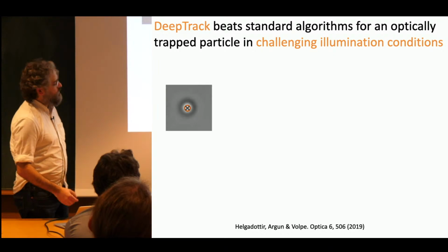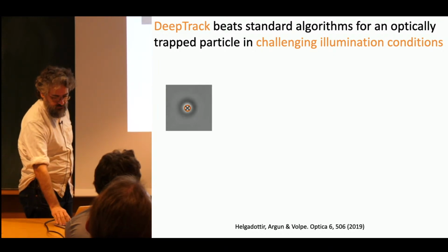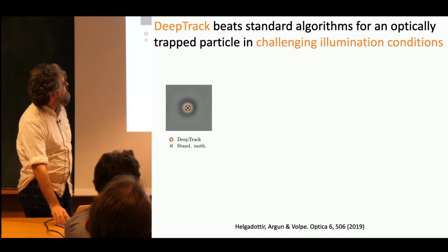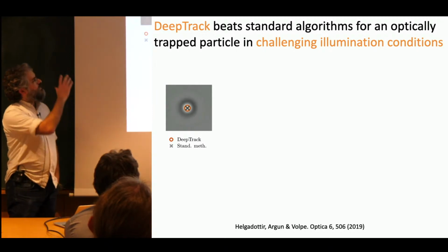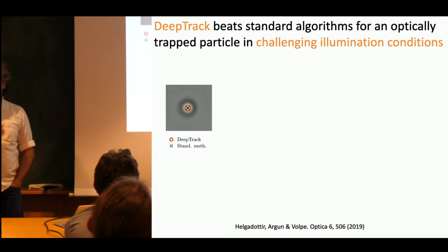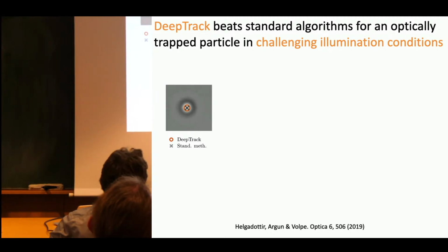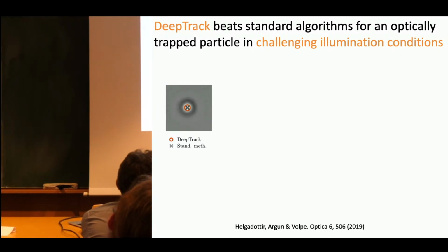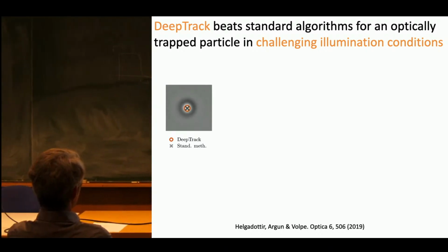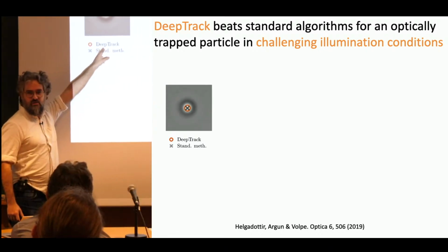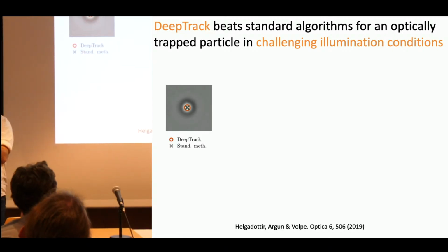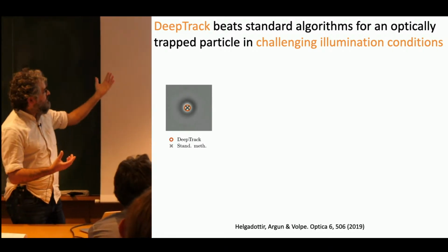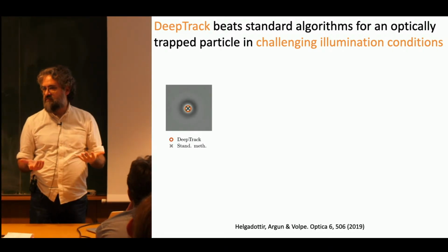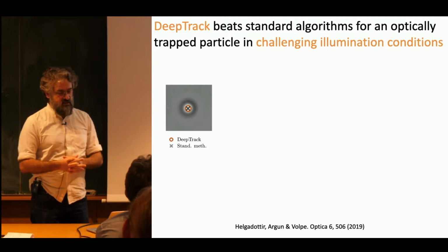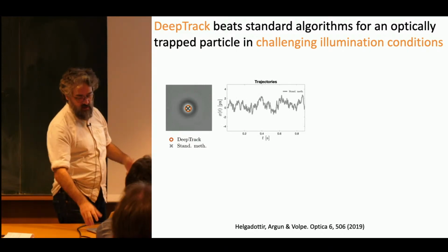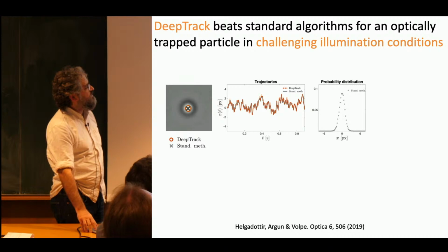And then what we decided to do was to try to see. Let's see if it runs. Yes. So you can see that in this case, we could track this optically trapped particle. This is a video of an actual physical particle held in an optical trap. And you can see that the standard algorithm and DeepTrack can track it perfectly, which is nice, but tells us that we can track. And if we compare the trajectory, they fit perfectly.